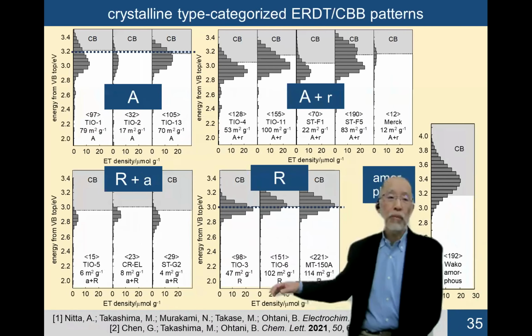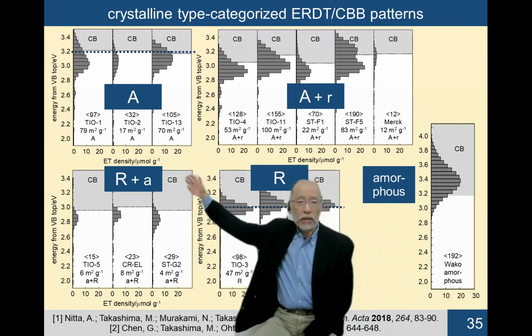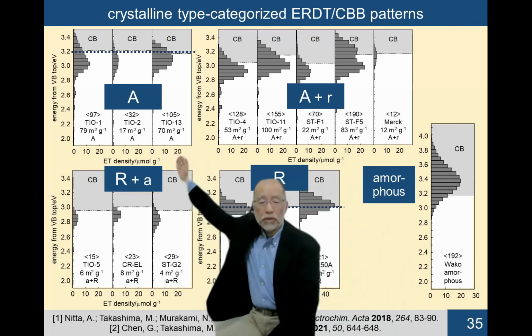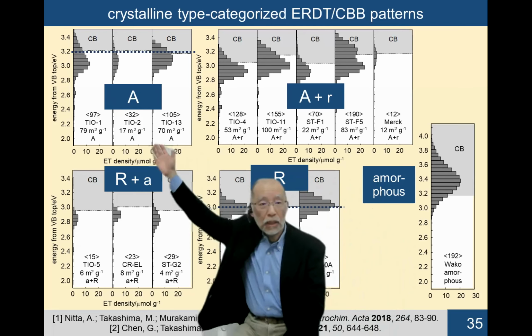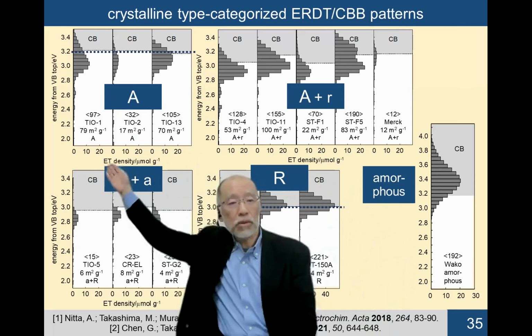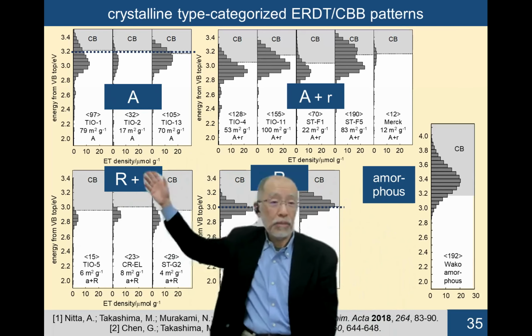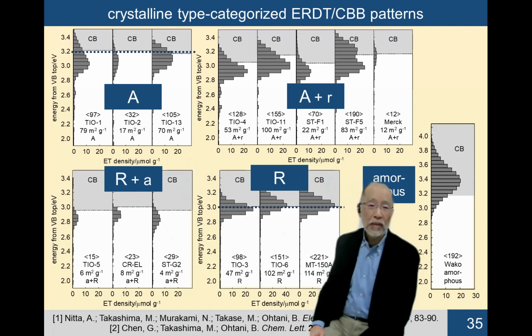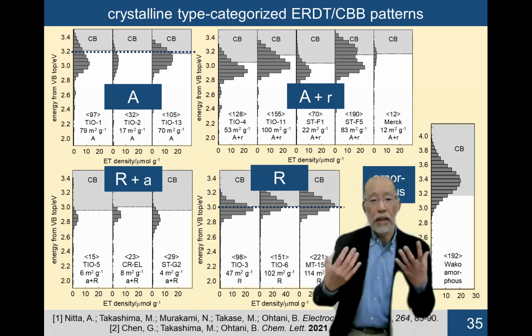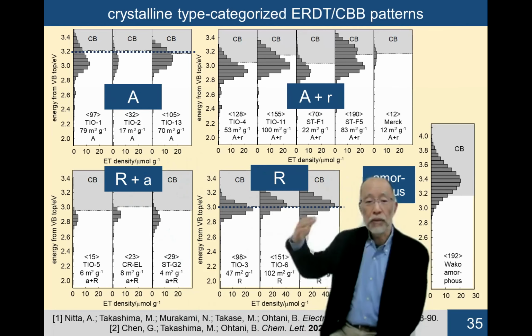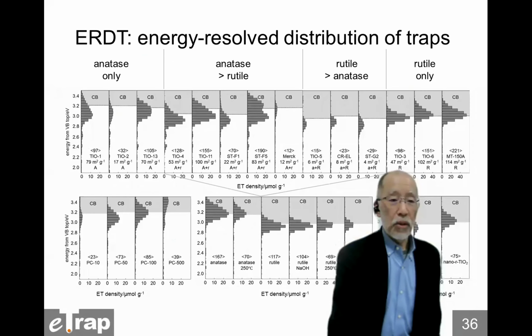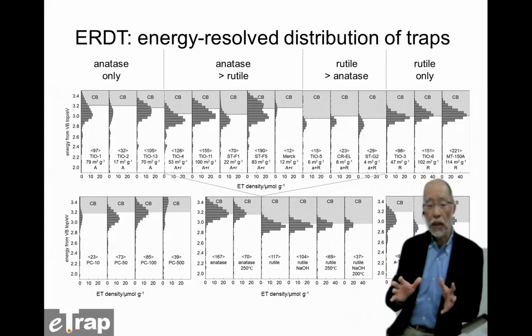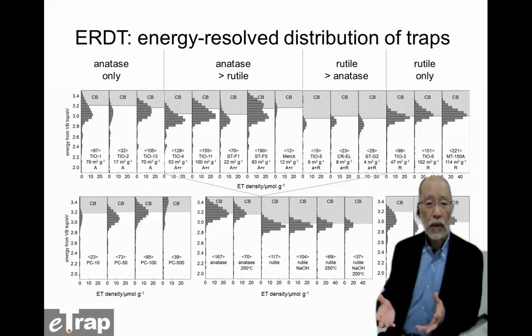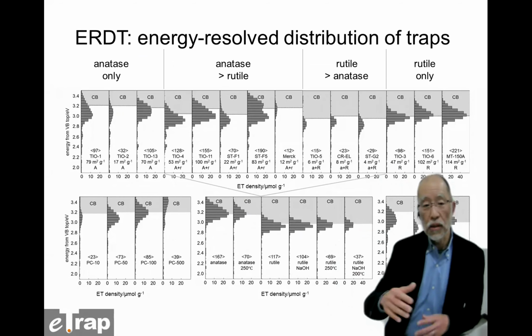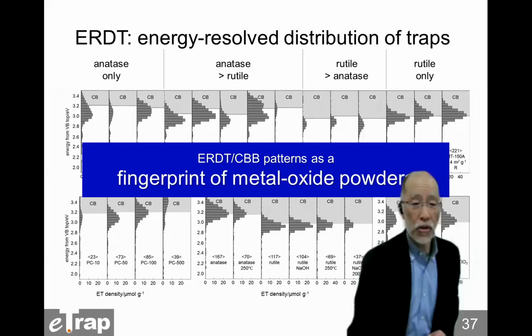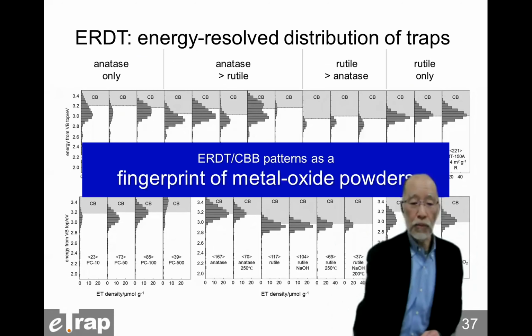And therefore, the anatase samples, for example TiO13 and TiO1, have almost the same specific surface area, but the pattern is completely different. So the ERDT pattern reflects the surface structure. This is only part of the commercial titanium oxide sample results, and you can see those patterns are completely different from each other, and that can be used as a fingerprint.